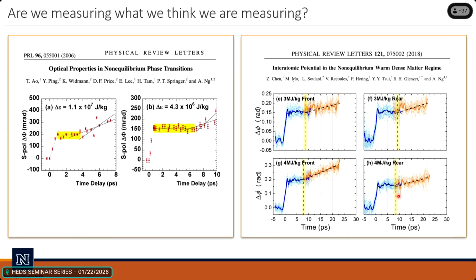And it matches two other papers. These are people who have shot similar gold foils with similar laser intensities. And they did FDI, so Fourier domain interferometry of the surface, to look for expansion. They also see no expansion up until melt, and then a sort of expansion after melt. And so this is why we have concentrated on the pre-melt stuff in all of our papers, because we don't really know what's happening after melt. And I cannot tell you the arguments that we have had amongst ourselves about why this solid, which is at eV temperatures, is not expanding. It doesn't seem to expand.